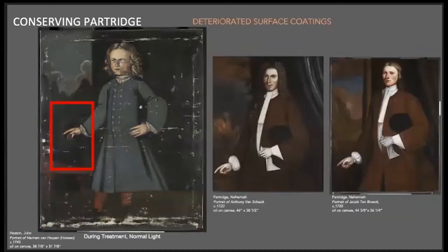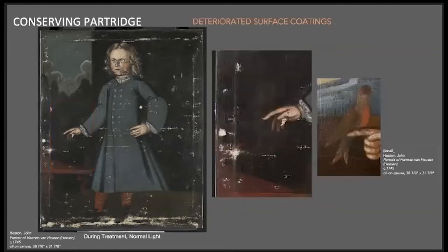It is believed that during a previous restoration campaign, the individual cleaning the painting had wrongly believed that the bird perched on the sitter's extended hand was non-original, and that the figure had originally gestured to the land in the background, similar to the two Nehemiah Partridge paintings on the right. So since he decided it was unoriginal, he proceeded with the cleaning and left an abraded surface. Unfortunately, it was not until after the restoration campaign that it was discovered that the bird was indeed original to the composition. The painting is currently in treatment, which involves the reconstruction of the bird.